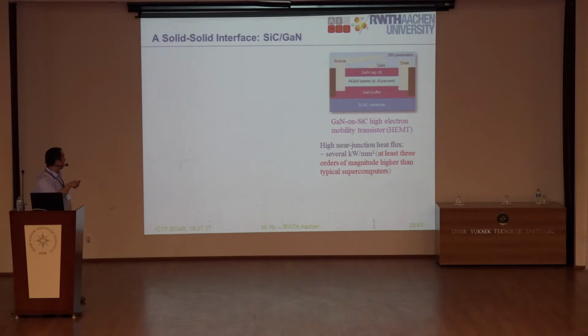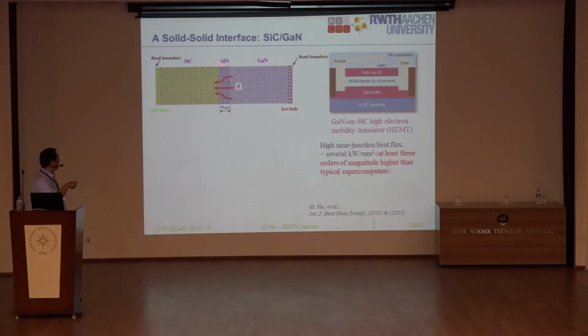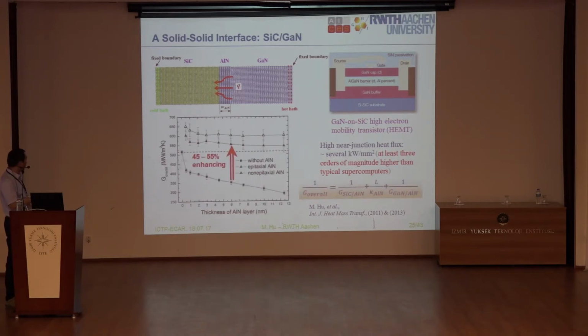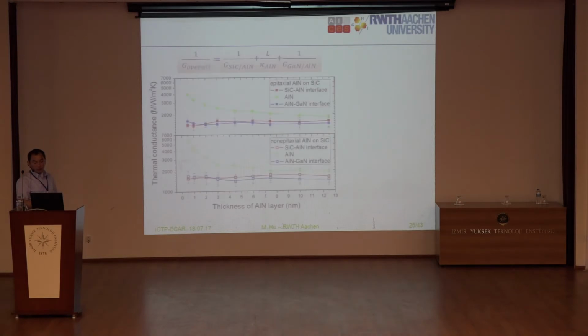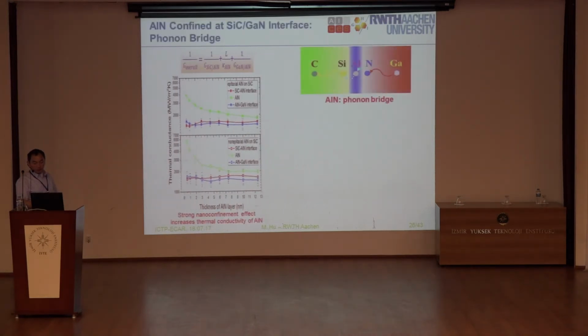We know that the high heat flux gallium nitride device is very, very popular for these HEMT applications, and also the near junction heat flux could be very, very high, several orders of magnitude higher than the typical supercomputers. And then the heat dissipation problem is a critical problem for maintaining the performance. So here we introduce the aluminum nitride, which is also widely used in the gallium nitride fabrication. So by introducing a very thin layer of aluminum nitride, actually the overall thermal conductance can be enhanced by 45 to 55%. So the mechanism, of course, comes from the phonon bridge like effect.